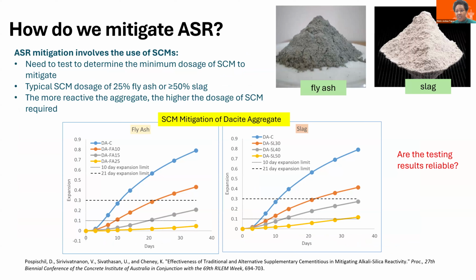Mitigation of alkali silica reaction involves the use of supplementary cementitious materials. This has been known for a very, very long time. The question then is, how much SCM do we actually need to mitigate alkali silica reaction? If we're talking about conventional SCMs, fly ash and slag, which have been around for several decades, with conventional chemistry we need about 25% fly ash or roughly over 50% slag to mitigate alkali silica reaction. The more reactive the aggregate, though, the higher the dosage of SCM required for mitigation. Therefore, we still have to test to be sure of the dosage required. But we already have a lot of documented cases, over 50 years or so, of structures that survive well, even with the use of reactive aggregates, when SCMs are in place to mitigate.